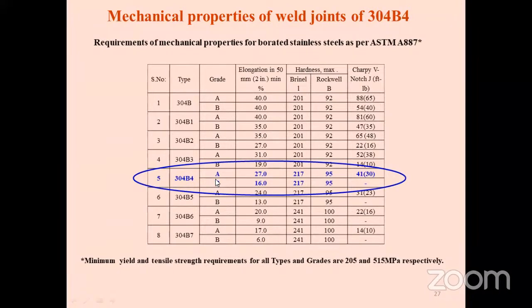Grade A material is manufactured by the powder metallurgy route, but grade B material is produced by the general ingot solidification technique. Because grade A material is produced by the powder metallurgy route, you have spheroidal borides, and it has better toughness as compared to the grade B material. So for applications where we are going for grade A material, the impact toughness is a mandatory requirement.